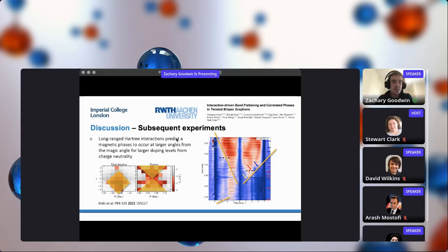Right, so I'm going to take a bit of a step back and look at the general twist angle and doping dependence of magnetic order. In the tight binding case, what we find is that as we move away from charge neutrality and magic angle, we expect basically less magnetic order to be observed. Whereas with the Hartree interactions, we actually find the opposite. So for larger twist angles from the magic angle, we expect magnetic order at higher doping levels away from charge neutrality.